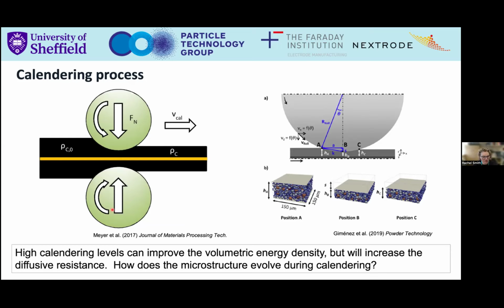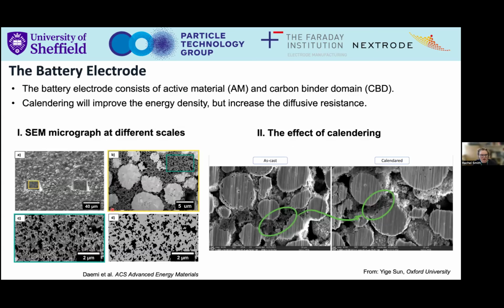So we know that if we have high calendaring levels, that can improve the volumetric energy density, but it does increase the diffusive resistance. What that means is that as we squish the electrode, we're making it harder for the lithium ions to travel through the electrode because we're reducing the space available for the electrolyte, and we're increasing the tortuosity. Arno spoke a bit about the tortuosity earlier. So we have this balance where we need to balance the improved energy density against the increased diffusive resistance. So how does the microstructure evolve during calendaring?